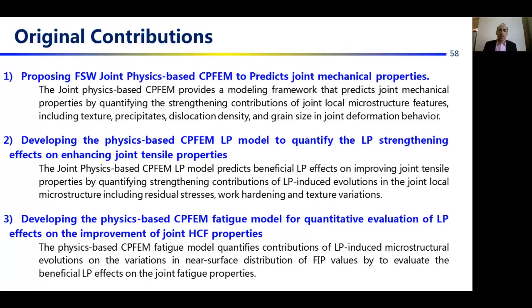as residual stresses, work hardening, and texture variations, and developing the physics-based CPFEM fatigue model for quantitative evaluation of laser peening effect on improvement of joint high cycle fatigue properties by quantifying the microstructural contributions on the FIP values.